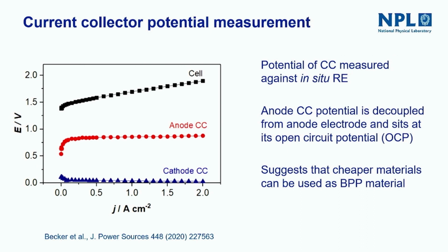And again, just like we predicted, rather than seeing the full 2 volts as you would at the anode electrode, we found that the current collector was completely decoupled from the cell potential. So there was a large potential drop through that deionized water layer in the porous transport layer.